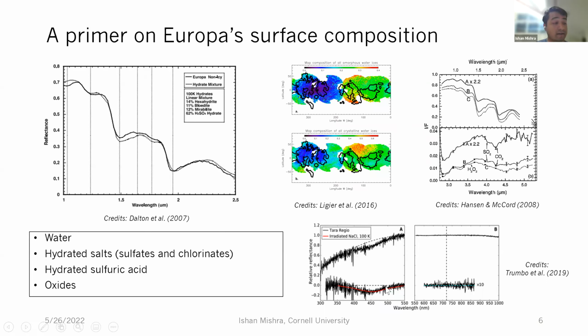And more recently, there was this exciting discovery of sodium chloride on Europa's surface. What was interesting was that sodium chloride is spectrally very flat when you just look at a regular sample of sodium chloride, but when you irradiate it with charged electrons, it develops new features called color centers. That is what was detected using the Hubble Space Telescope. And more interestingly, it was detected in regions that are geologically younger, so it mapped pretty well to those regions, pointing to probably sodium chloride coming from the interior, which would make the ocean more similar to ours.